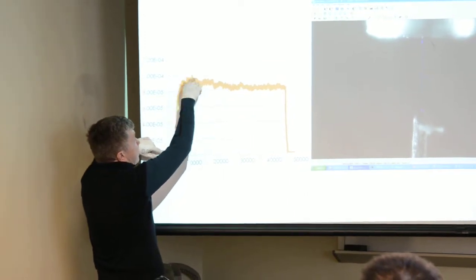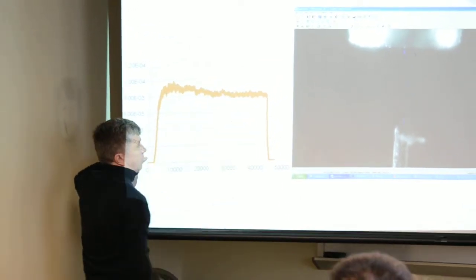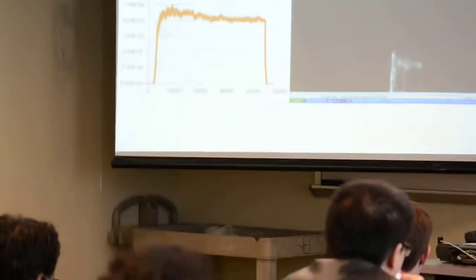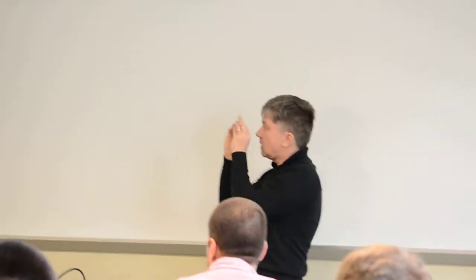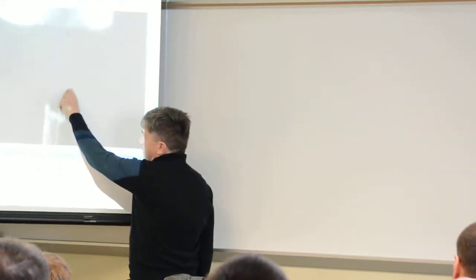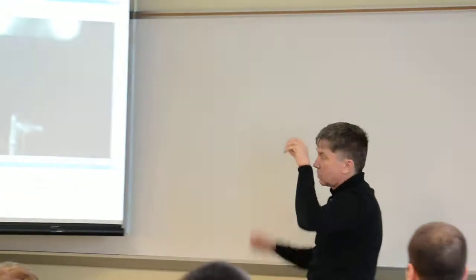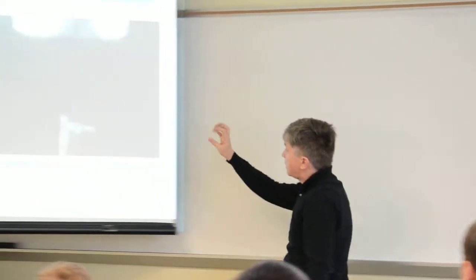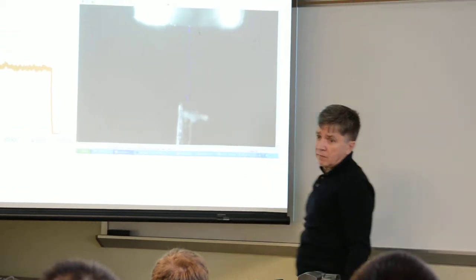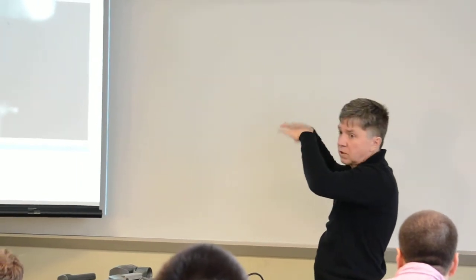You come back after lunch and see the curve decay. When sitting at the top, there's some fluctuation in the current. Despite constant voltage, if you sit and eat lunch while looking at the computer, you may see little glowing spots. These are little antennas, tiny rods sitting there. Some carry so much current that they start to burn. The tip evaporates. You literally see little lightning, flash, and you're killing some tubes. The tubes being killed lead to current fluctuation even at 1000 volts.